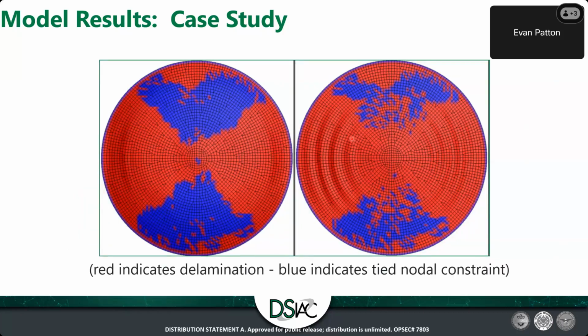These two plots here, this is the delamination of a specific interface between two composite plies. Red is bad. Red means that it is delaminated. Blue is good, meaning it's still acting as essentially one system. And the two different plots, I wanted to add two different ones for the point that the one on the left is at peak deflection, and the one at the right is sometime after when we pulled the specimen out of the test chamber, and there's no additional loading.